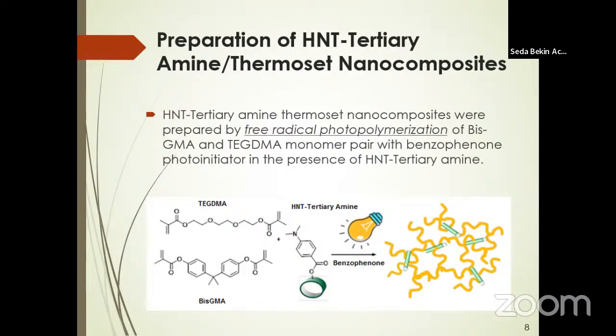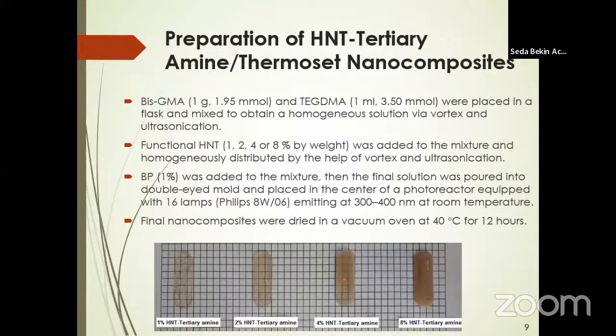Thermoset nanocomposites containing functional halloysite were prepared by free radical photopolymerization of multifunctional methacrylate monomers with benzophenone photoinitiator in the presence of halloysite tertiary amine. You can see the final structure in the figure. For this purpose, the multifunctional methacrylate monomer pair was placed in a flask and mixed to obtain a homogeneous solution via vortex and ultrasonication. Tertiary amine modified halloysite was added to the mixture at 1, 2, 4, or 8% by weight and homogeneously distributed with the help of vortex and ultrasonication.